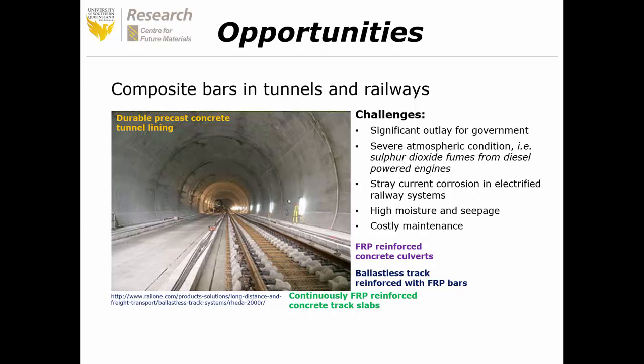And also in tunnels, the level of moisture and seepage is very high, causing significant corrosion to steel reinforcement, leading to costly maintenance. So let's say we use FRP reinforcement in precast concrete tunnel lining, concrete culverts, ballastless tracks, and also continuously reinforced concrete track slabs. If we consider using FRP bars, then we can assure that the corrosion of steel reinforcement will be eliminated, and we can develop a tunnel structure that is ensured to have at least a 100-year design life.